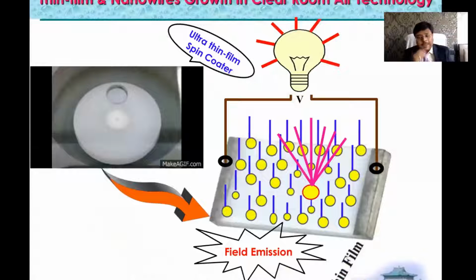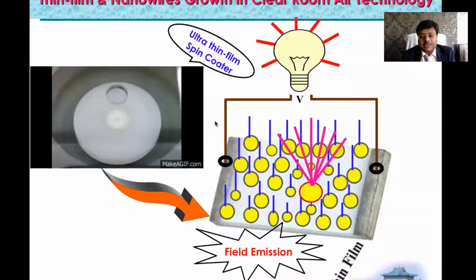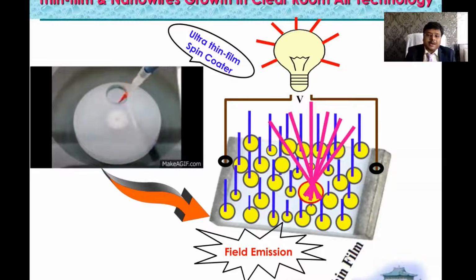And this is another technology, called vertically aligned nanowires. First we obtain the seed particles. When the seed particles are obtained, we then grow vertically aligned nanowires on them by thin film deposition with a programmable spin coater, and we also measure the field emission. The sharper and longer the ultra-thin nanowires are, the higher the emission we will get. That is most important in this case.